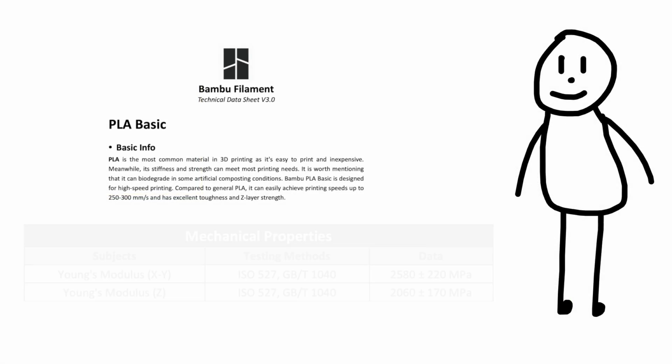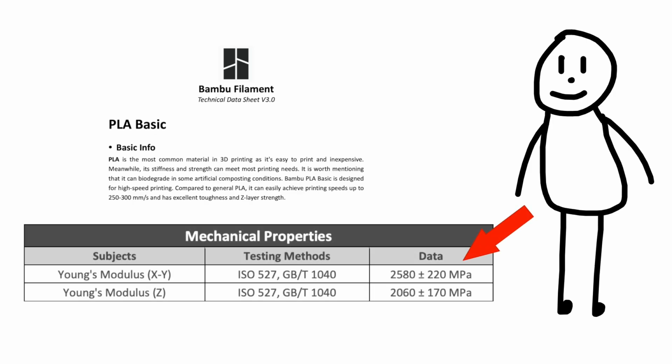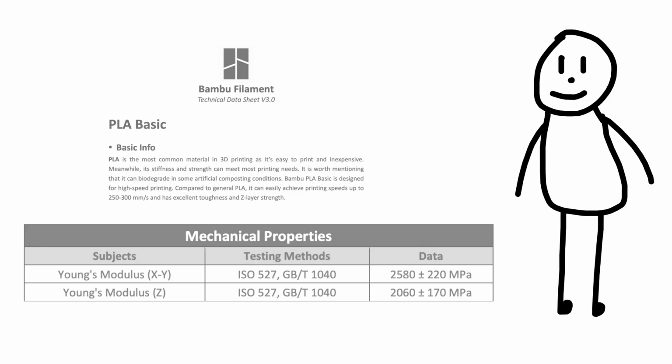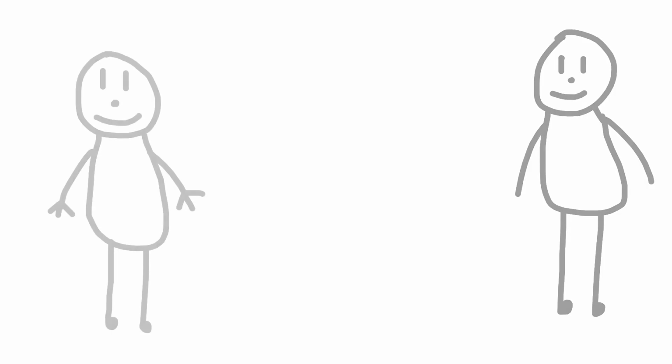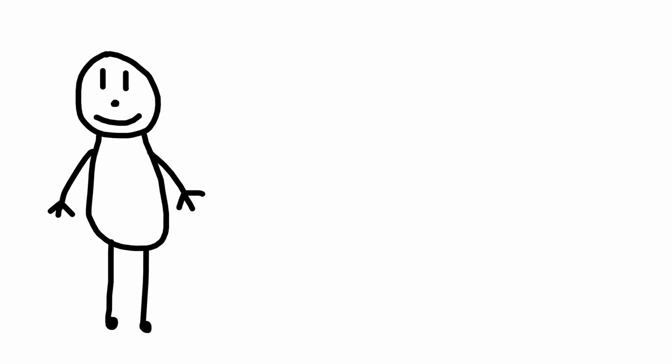This is significantly below the value of 2.5 gigapascals listed on the technical datasheet for XY bending modulus, and instead much closer to the Y value. This conveniently brings up something important to mention. The strength of 3D printed parts vary a lot by print orientation, with XY being vastly stronger than the layer stacking direction, especially for the fiber-filled composites, which I'll come on more in a bit. First, I need to print off the test strips from all the other materials and finish the testing.